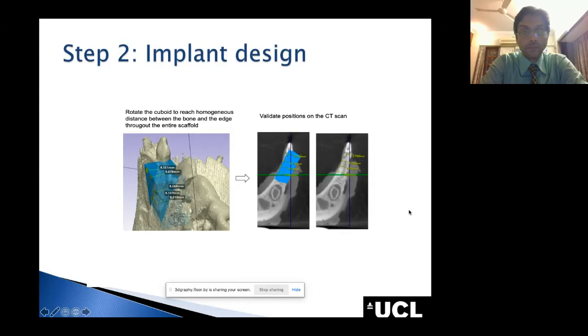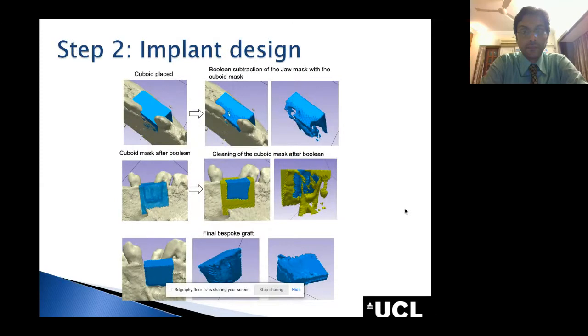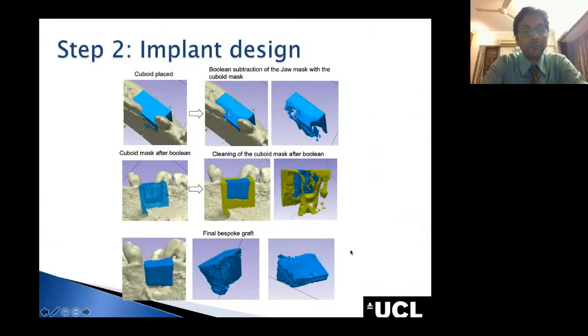Once we were happy, and once Federico was happy with the placing of this cuboid, we then decided to clean up and remove whatever was not necessary for the defect we created, as you can see here, and we removed this mask. After this step, we end up with a graft, and as you can see here, there are many irregularities on the surface, and this will not be accounted for in the slicing software. It will not be detected.